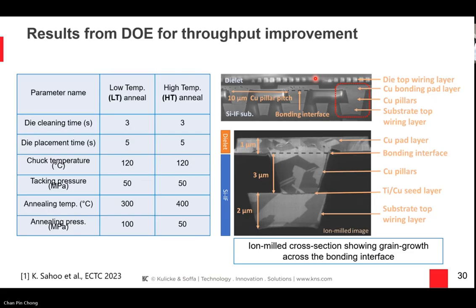Yeah. So this is an example of some of our current process. We have two processes, one is called a low temp anneal, and the other is a high temp anneal. And obviously, we like the high temp anneal, but there are many cases where the low temp anneal is the one that we have to use because of various other constraints. And so today, the die cleaning time is about 3 seconds. The die placement time, which is a big component, is about 5 seconds. And then we have the chuck temperature, which is the substrate temperature, which is held at 120 degrees. And the die temperature is also the same temperature while we do the alignment.